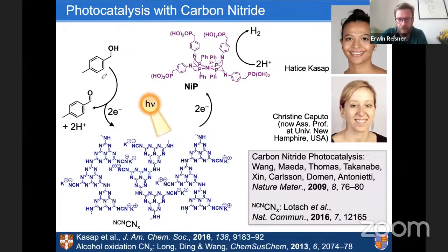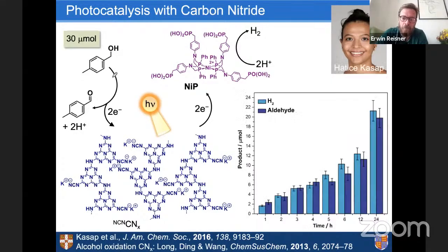So now you could well say, well, benzyl alcohol is a known sacrificial reagent, but I would argue against it here, simply because we could show that we could use really low amounts of benzyl alcohol, which means 30 micromole, and in the process convert this alcohol very cleanly with almost quantitative selectivity to the aldehyde in 70-80% yield. So it's not just a sacrificial reagent where you form a range of different products and have a huge excess of substrate. This is a proper clean stoichiometric conversion. Interesting in the context of what is sacrificial and not, but in this case, I would argue against it. I think it's a clean transformation. It's not an interesting one, but it is an organic transformation.